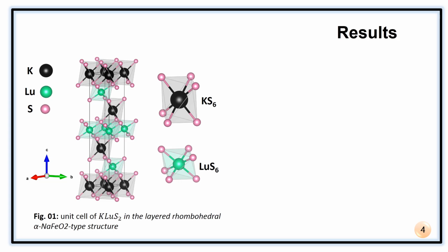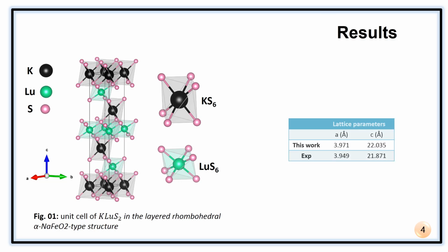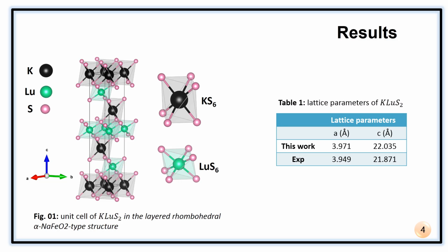Okay, let's now move on to the results. This figure summarizes the crystal structure of the considered material. As you can see, potassium lutetium sulfide is formed by alternating layers of potassium and lutetium, and each layer of potassium or lutetium is surrounded by 6 atoms of sulfur. Our obtained lattice parameters are presented in table 1, and we can clearly see that our results are in good agreement with the experimental data, which is a good starting point for this work and very important.